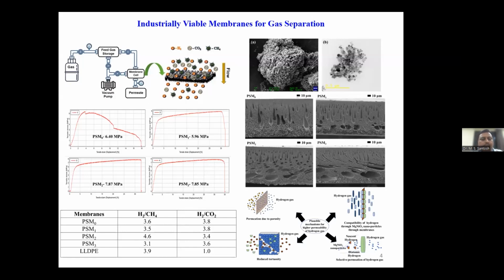great level. We also performed mechanical characterization studies in order to study how durable these membranes are and what the strengths of these membranes are. And as you could easily make out from the results, the graphs shown here, the strength of the mixed matrix membranes gradually increased when nanoparticles were introduced into the polymeric surface. On the right-hand side, you can see the cross-sectional image of the membranes where different porous surfaces are being shown. These cross-sectional images clearly indicate how the pores are formed on the surface, and the nanoparticle facilitates the penetration of hydrogen, or the separation of hydrogen, effectively through the membrane.